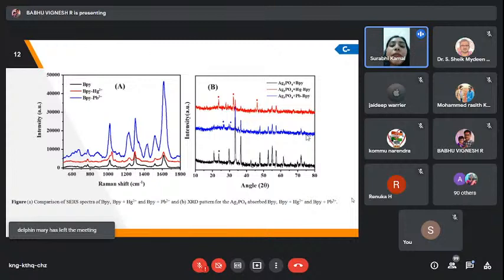Here is the application part of the SERS. What I have done here is I have taken the SERS spectra of just bipyridine, and then I have added mercury, and you can clearly see the intensity rise as well as the peak definitions. There are extra peaks because of the Ag and Hg, and then I have added the lead. So you can see a huge peak difference. Intensity change is what is important in SERS, so the molecules are very easily detectable and you can easily identify them. I have also done the XRD with different metal additions, and each of the peaks talks about the presence of the metal in the XRD.